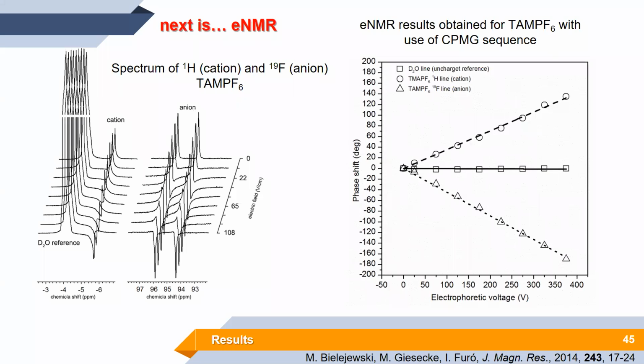get direct evidence and information about two key parameters. This is the electrophoretic mobility and the effective charge of diffusing ions. And this applies for cations, which mostly have protons in their structure, so it's very easy to measure with NMR, and anions, which have other nuclei-active species that can be measured.